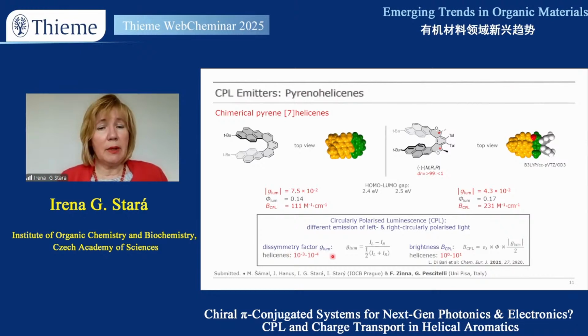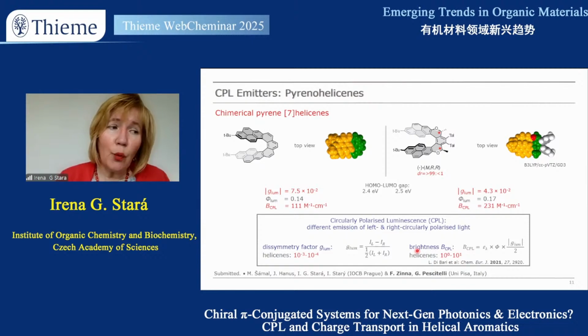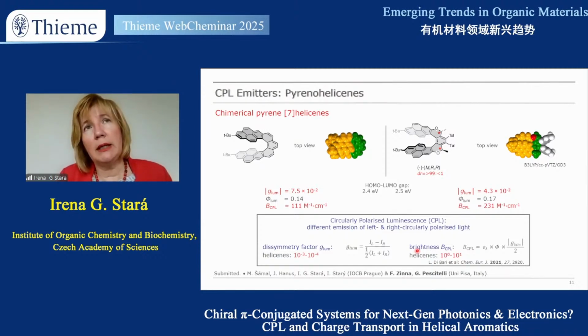Here is the equation, which includes the intensity of left and right circularly polarized light. For helicenes, the range in which the dissymmetry factor g_lum is usually observed in the literature is 10 to the minus 3 to 10 to the minus 4. I forgot to say that the range of g_lum is from -2 to +2. And because we have different materials to compare, the dissymmetry factor alone will not fully characterize these materials.